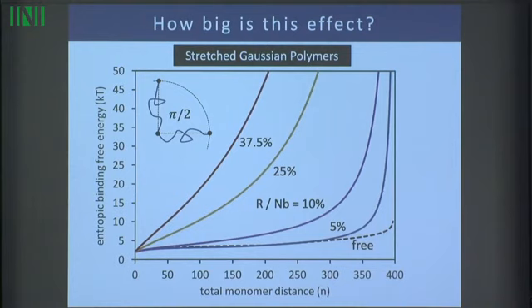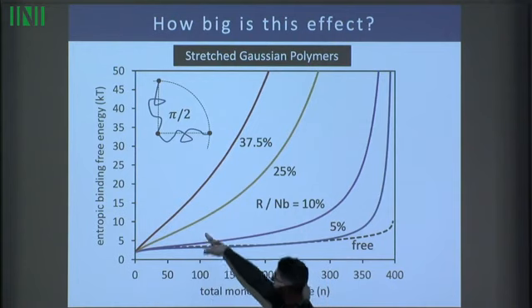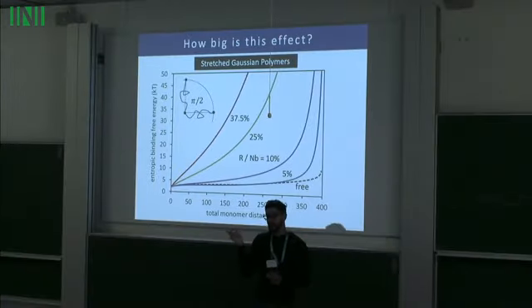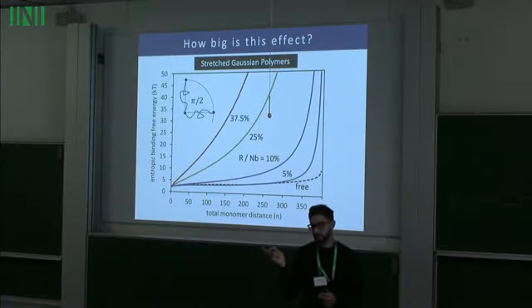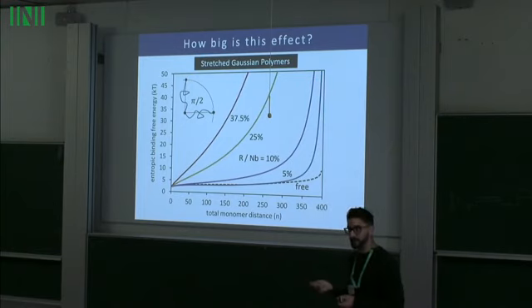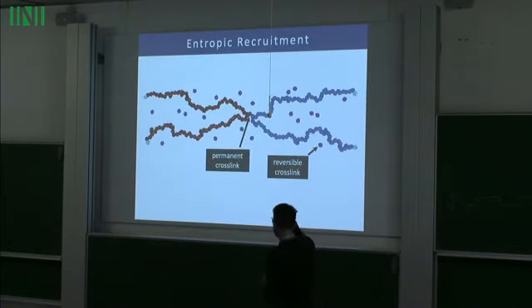So you can see in the case of the 25% stretched chain, it's not very stretched as a polymer, but already if I make a loop that's of size 100 monomers, I'm getting an entropy cost of around 10 kT, which is actually quite large in terms of molecular properties. Okay? So in polymer networks, we can expect there's quite a strong driving force for this entropic clustering. Okay? So we wanted to think and to see if this happens in a more realistic system.